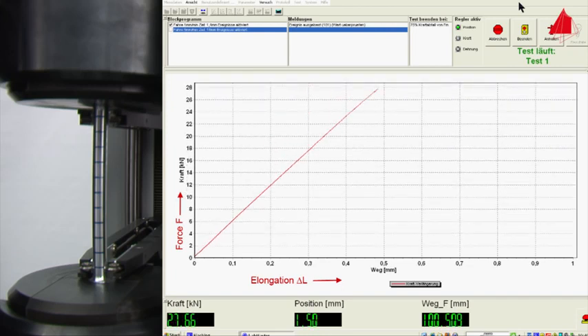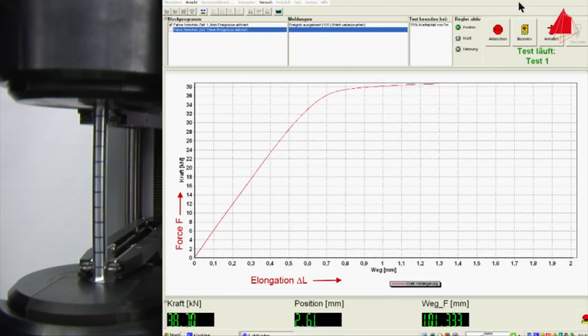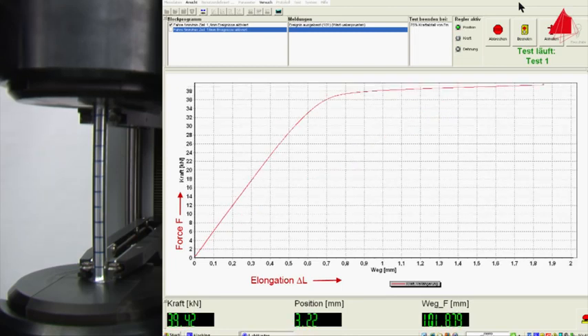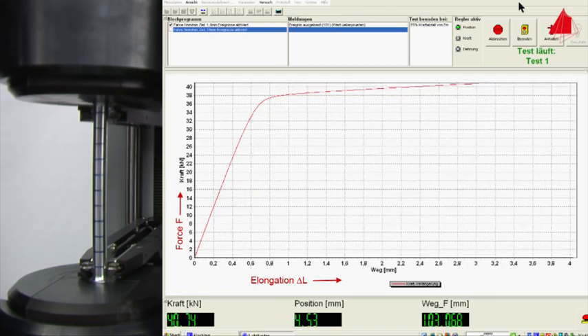But this time the end of the elastic area is not revealed by a sudden drop of force or any distinct change. There is a smooth and gradual transition from linear elastic behavior to plastic deformation.